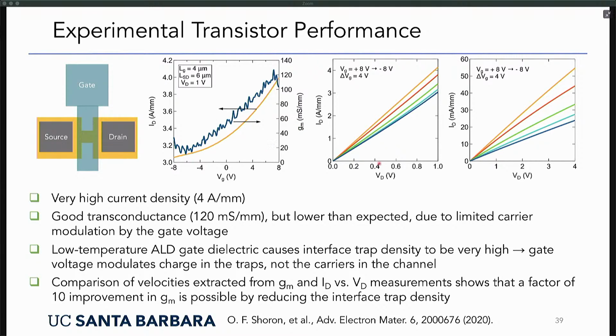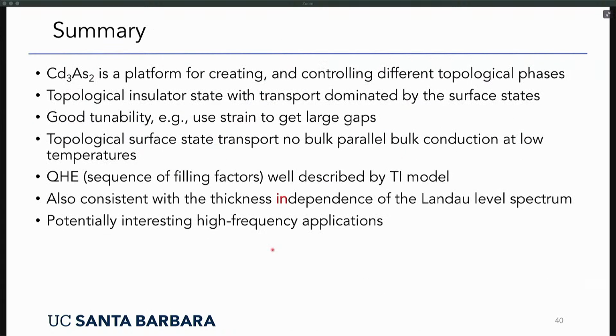Okay, but estimates are that if you would reduce these trap densities, you could at least get a factor of 10 improvement in the transconductance, and already this transconductance is actually quite good. So these initial results, without optimizing things like the interface between the gate dielectric and the cadmium arsenide, are actually quite promising. So with that, I'd like to sum up my talk.